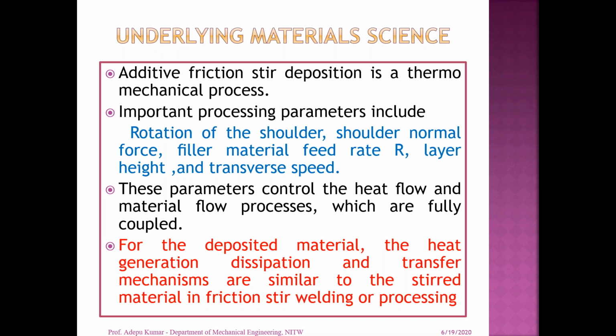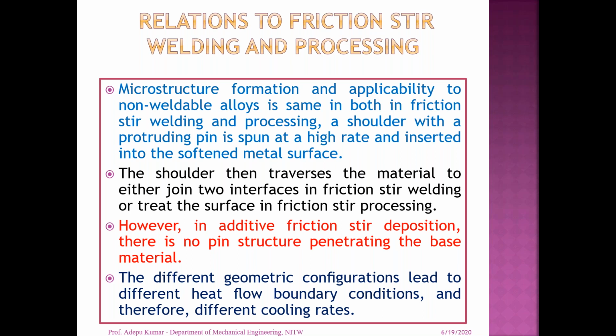Microstructure formation and applicability to non-weldable alloys are the same in both friction stir welding and processing. A shoulder with a protruding pin is spun at a high rate and inserted into the softened material. The shoulder then traverses the material to either join two interfaces in friction stir welding or treat the surface in friction stir processing. However, in additive friction deposition, there is no pin structure penetrating the base material. The different geometry configuration leads to a different heat flow boundary, and therefore different cooling rates. In additive friction deposition there is no pin because of the provision for feeding material, so there is a lot of difference in the heat generation.